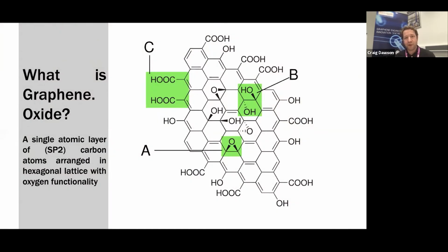So graphene can also be made in another way. We can make it chemically, and we produce this oxidized version. So, back to chemistry 101, graphene is this perfect honeycomb lattice. So ignore all those O's, OHs and COOHs, and just imagine that as a perfect lattice. And that is what pristine graphene is, this sp2 carbon structure. When we produce it chemically, you use quite aggressive chemicals, and it introduces these oxygen-containing groups, and that's called graphene oxide. I've mentioned that because I'll mention it through the rest of my talk.